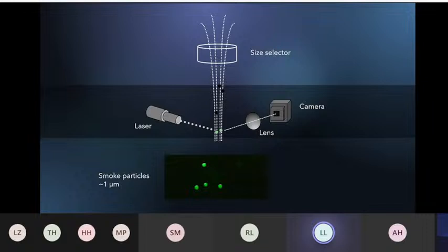So what you see here is an image of smoke by burning paper. This actually generates particles around 1 micron and even smaller. And we are able to detect these particles, and so we are also able to count them. So in fact, just by doing some image analysis, we have come up with a very simple and effective measurement scheme. So it counts explicitly and then translates the particle count into concentration.